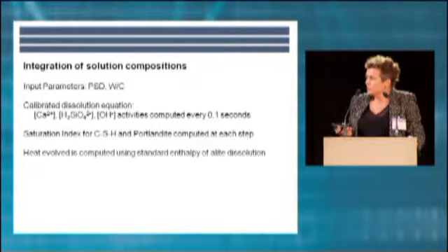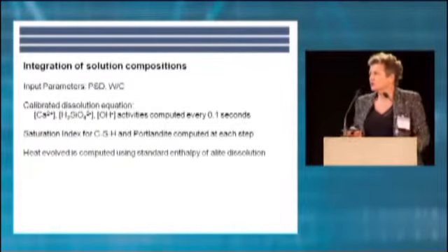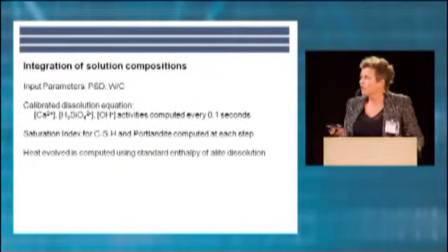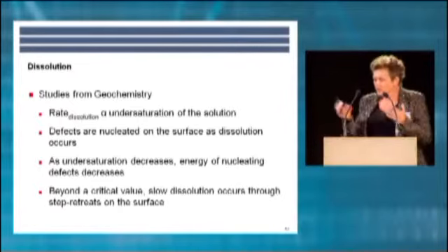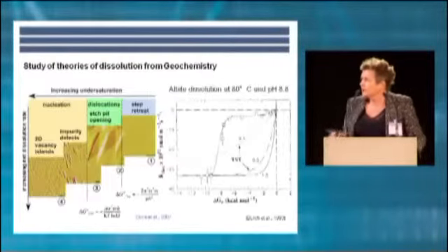We put in the particle size distribution, the composition, the water-cement ratio, etc. We can represent how the different concentrations in solution evolve on a scale of 0.1 seconds. We can calculate what phases can be precipitating, and we can use the models from other fields.